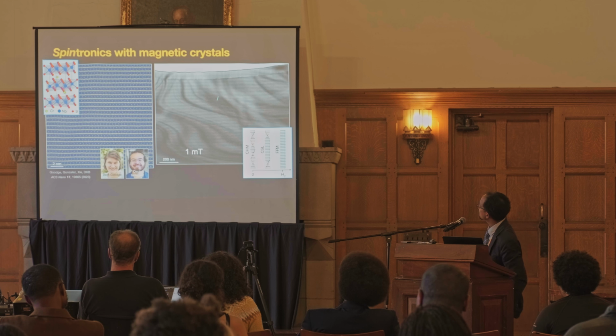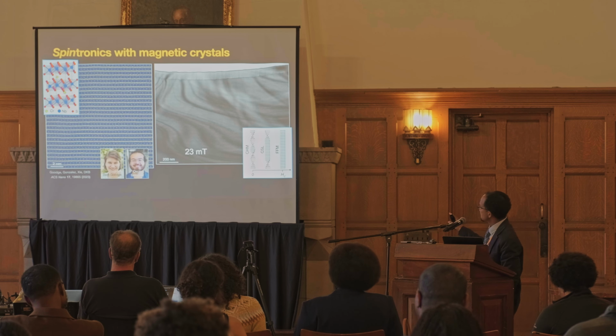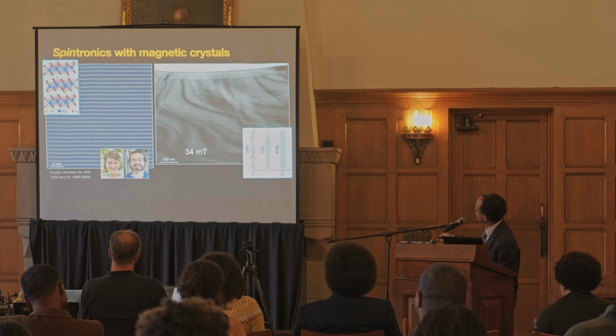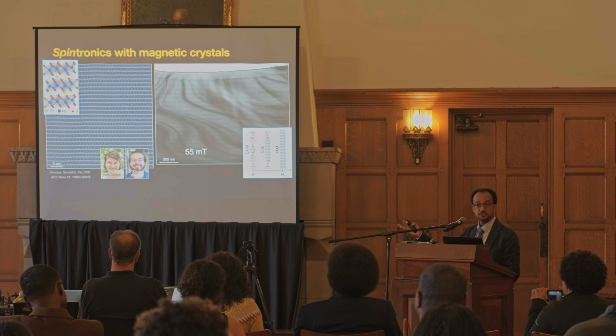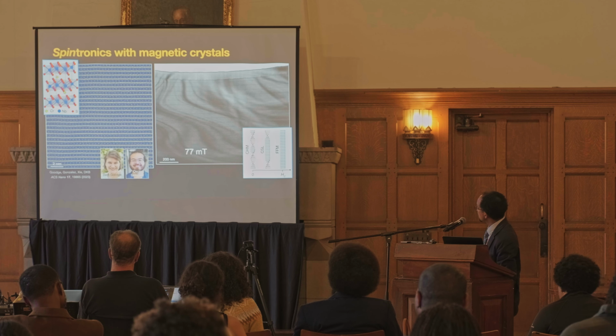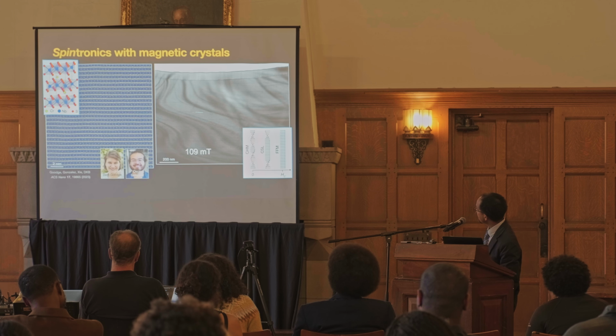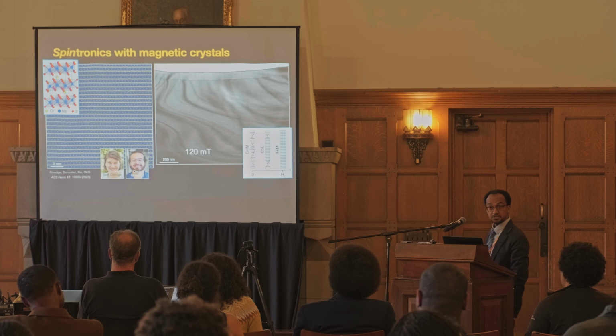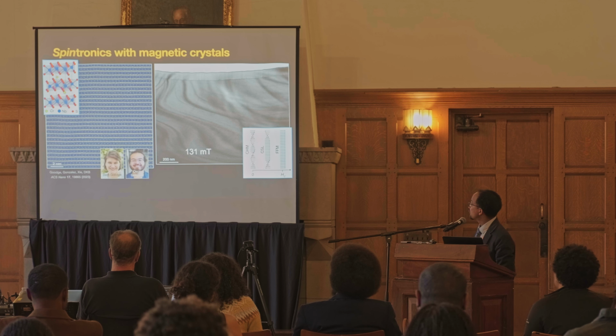I'll give you an example. Here what you're looking at is a material where the spins form a helix. And what we're doing here, if you follow closely, as a function of magnetic field in the electron microscope, we are watching how those spins reconfigure. As we apply more and more magnetic field, we take that helix and we unwind it continuously. So you see these horizontal lines. We unwind them until at some point they vanish completely. And so this is a way of effectively storing information in how many coils, how many windings there are in the magnetic material.